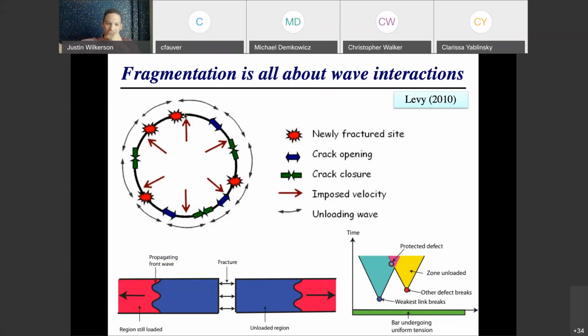So if that guy fails a few microseconds ago and you don't get the information in time, you're going to keep stretching and stretching, and then you may fail as you reach your local failure condition at that point. And so that's kind of the idea of fragmentation, and that's why you tend to get smaller and smaller fragments as you load a material at faster and faster rates, because the speed at which that information comes to you about the release is fixed. That doesn't depend on the loading rate. And so if you're loading very, very fast, then you're going to take more of the points to their failure before they receive that release information.